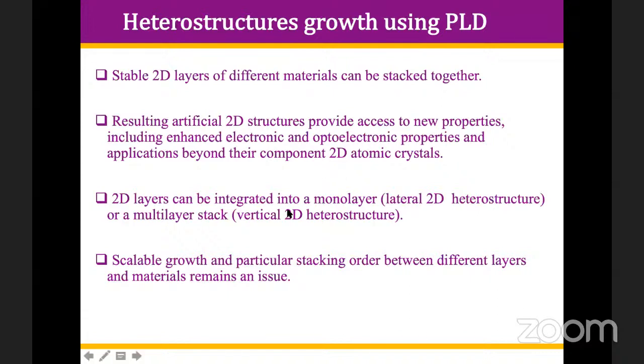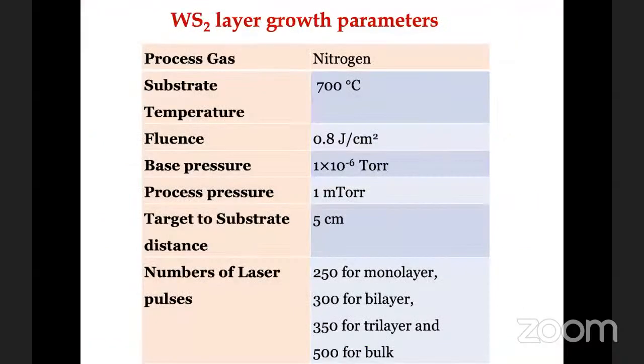This 2D layer can be integrated into a monolayer if we are integrating in the lateral two-dimensional heterostructure, or we can make multiple stacks if we stack one over the other in the Z direction. But the problem is again that scalable growth and a particular stacking order between different layers and materials remain an issue. Those are the challenges. So we used another 2D material, WS2, and we want to make the heterostructure of MoS2 with WS2.